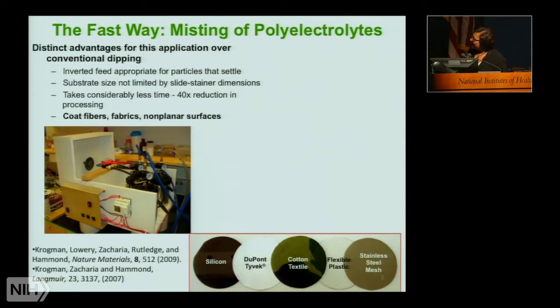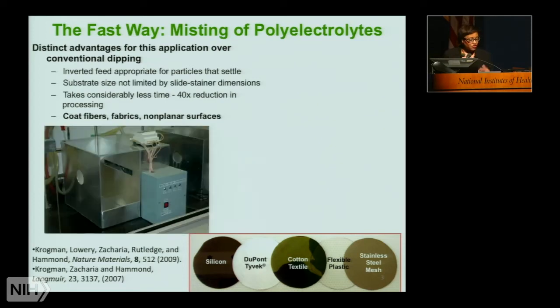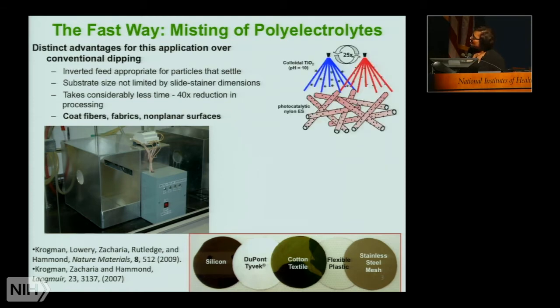And this is actually a homemade automated spray layer by layer system built by one of my former students who later went on to start a company which made these micro sprayers and then went on to generate large-scale layer by layer systems which can generate 50 feet per minute of huge yards of layer by layer materials. This demonstrates the fact that this is scalable, but spray layer by layer has also allowed us to coat a broad range of substrates, everything from very highly porous substrates to flat ones.